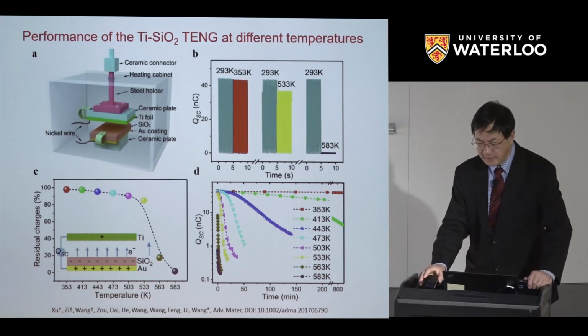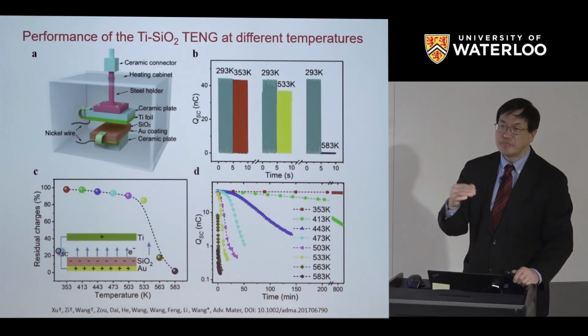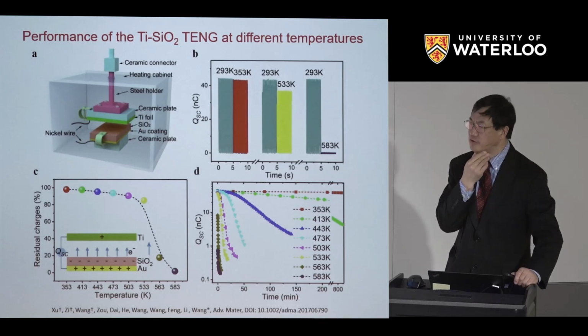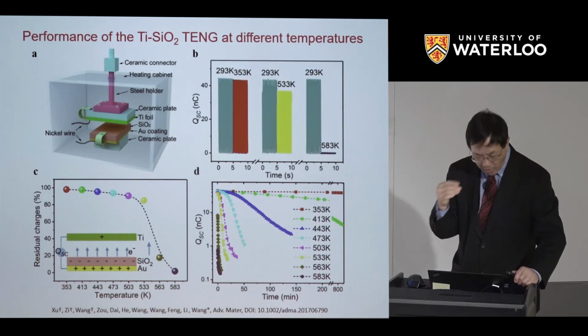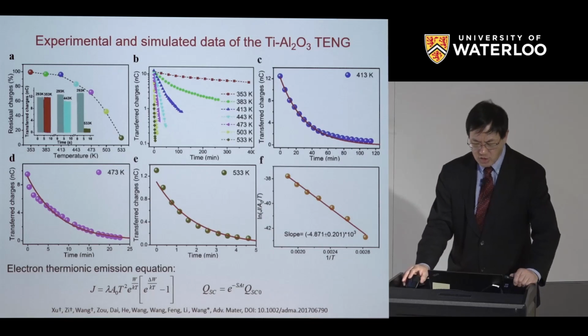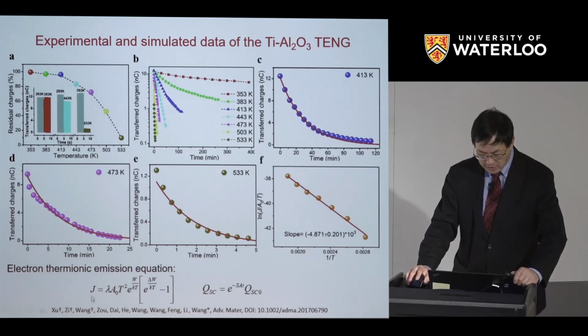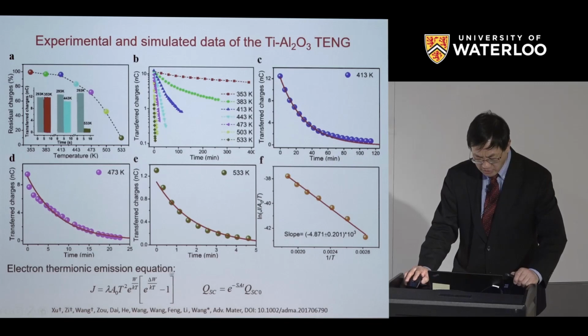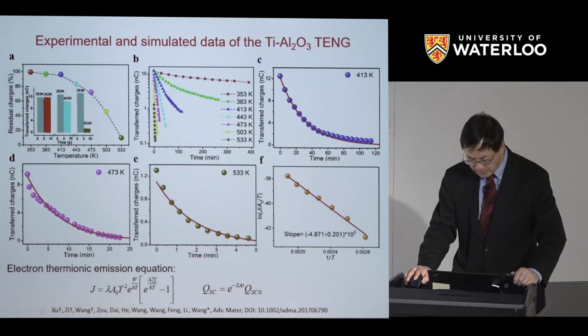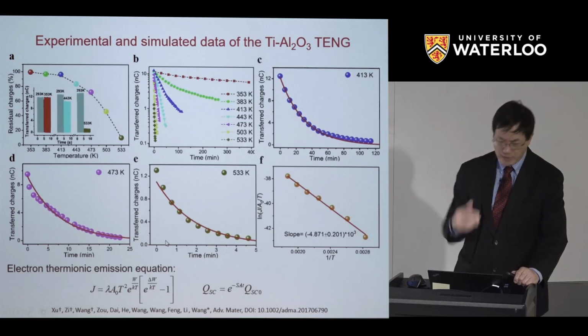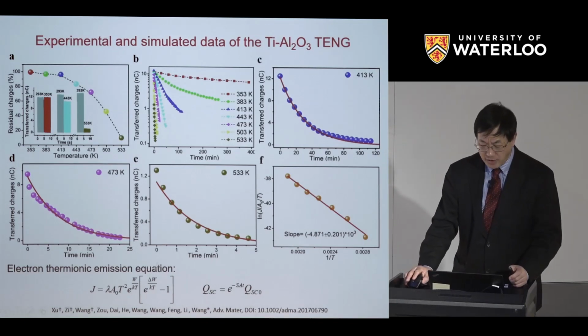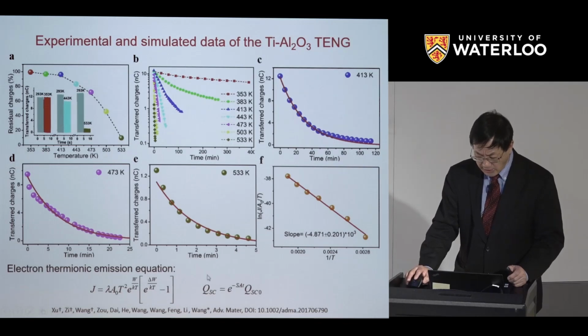So what this means is that this is an electron emission process, thermal emission process. So we use the thermionic emission model to model our data. We find that based on the electron thermionic emission equation, there's a potential barrier here. And the electron has to overcome this potential barrier in order to transfer from one place to the other. So we find this is electron transfer here, and it's also related to overcoming a barrier at the interface.